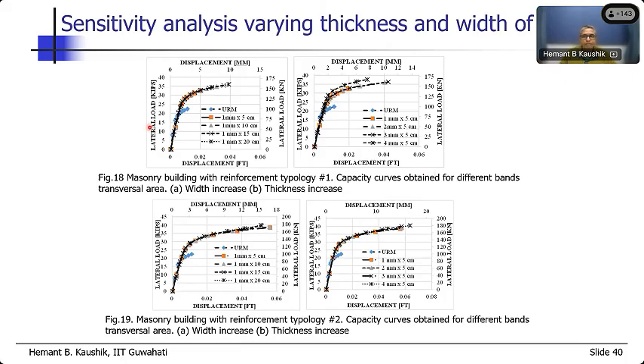This is the numerical analysis in which we use different sizes of the steel flats. You can see here 1 mm thick by 5 centimeter wide, 1 mm thick by 10 centimeter, 1 mm thick by 15 centimeter, 1 mm by 20 centimeters. 4 different types of steel flats were used. Here we used same width of the flat, but we changed the thickness of the flat. Right? So 1 mm, 2 mm, 3 mm, 4 mm, keeping 5 centimeter as the width of the flat. And this is for the scheme 1, and these results are for the scheme 2.